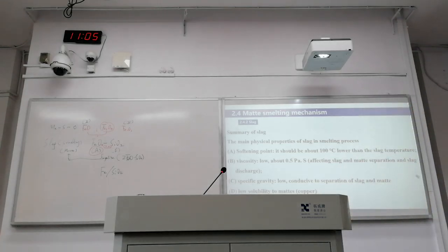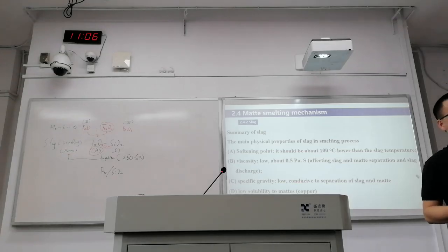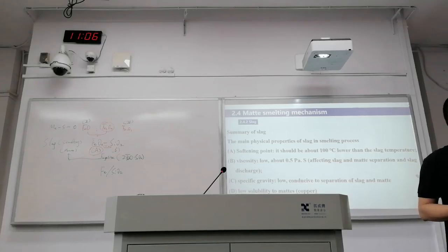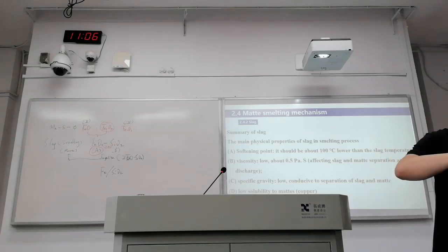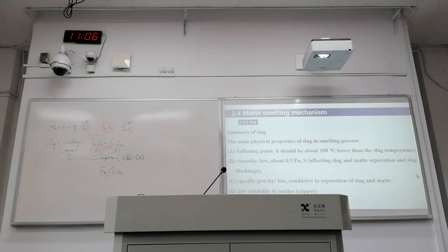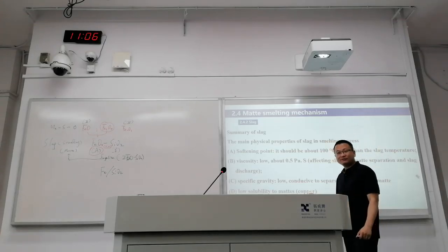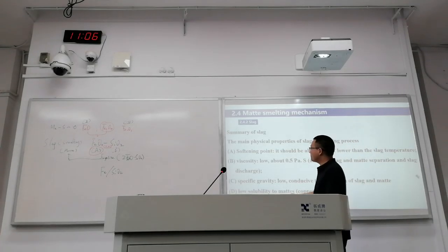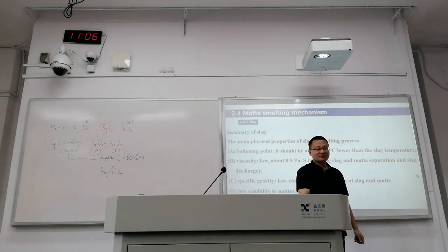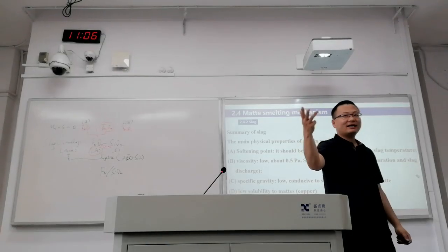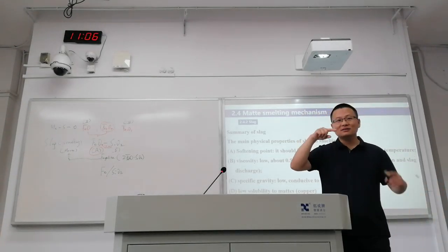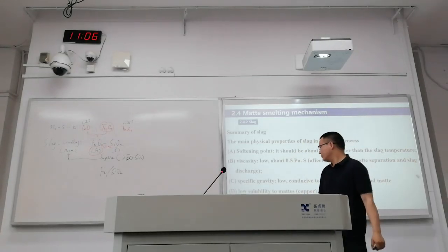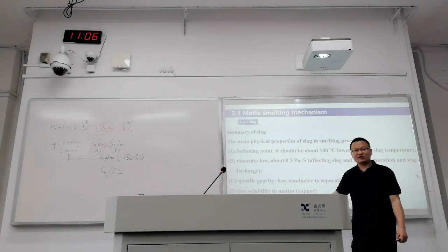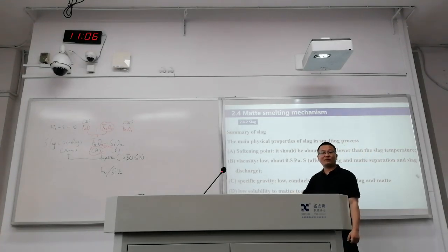So for HPAL, the reactor is a problem. You know what the material in the reactor is? Titanium, or lead. They are manufactured in China and transported into Indonesia. They are very inert in those conditions. And here, we have a metal phase, a sulfide phase, and if you are talking about the slag, an oxide phase. So oxides, sulfides, metal, and gas: four different phases in the same reactor. So the refractory will face a very strong test. So the corrosion is a very big problem.